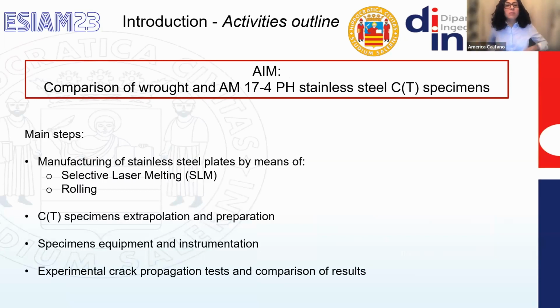The activities were based on a few main steps. So first of all, there was the manufacturing of the stainless steel plates by means of, on one hand, the selective laser melting technique, and on the other hand, the traditional rolling technique. The CT specimens were then extracted and prepared. At least the additive manufactured specimens were subjected to metallographic analysis. Then the specimens were instrumented, and finally subjected to crack propagation tests, and the obtained results were compared.